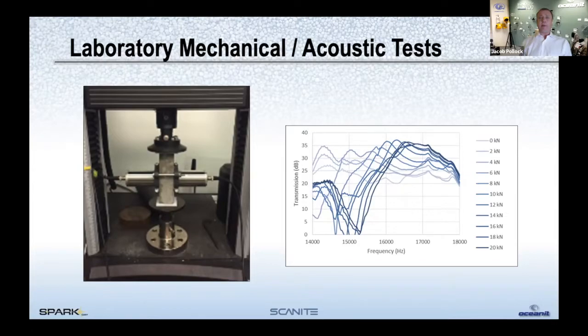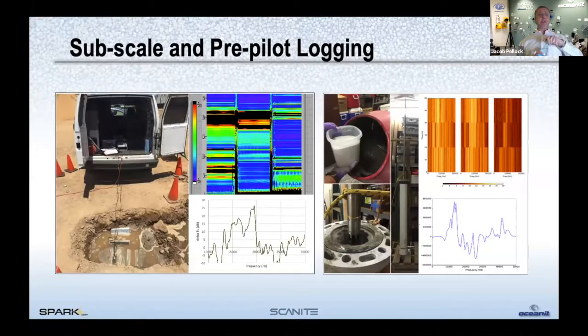Not only do we detect this acoustic band gap effect, but we actually saw a change in the acoustic band gap response upon mechanical loading — really exciting, because of the concept Hany described: essentially turning the entire cemented wellbore into a strain sensor. The left shows our lab setup in a mechanical testing system with ultrasonic transducers, and the right shows some of the shift in acoustic response with increased mechanical loading. We took these structures — some just cement composites, others cement composites behind steel sheeting — out to do some sub-scale testing in a semi-submerged environment.